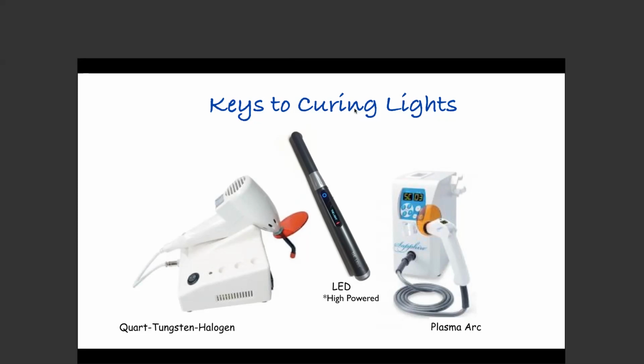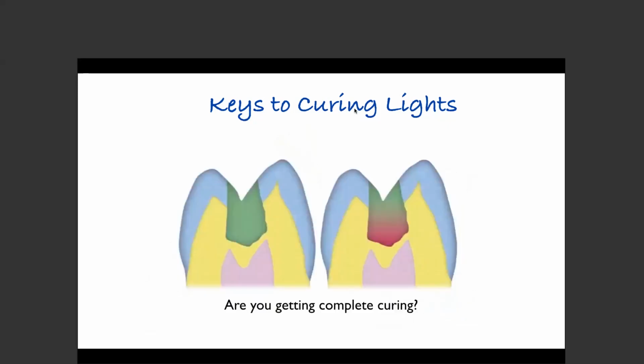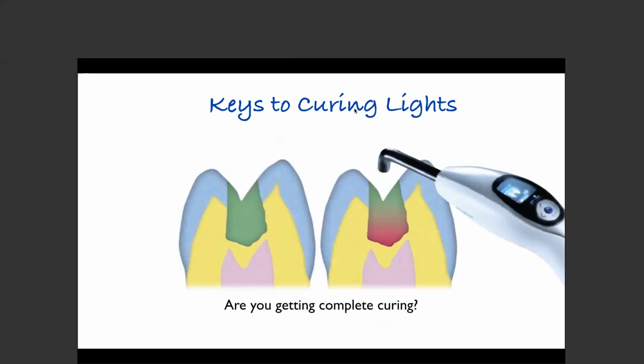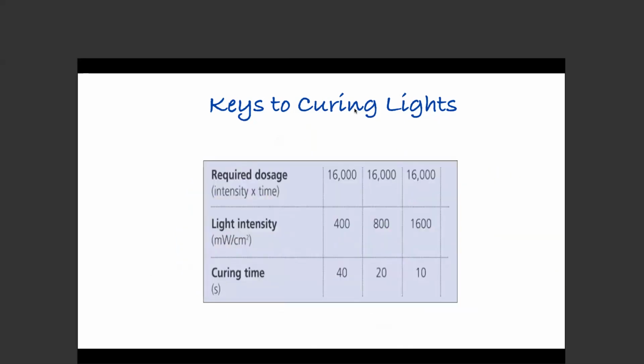And in my world, I believe that those curing intensities degrade much faster over time. The halogen bulb doesn't last as long, doesn't kick out as much power a year from now as it does when a new bulb is placed. So just make sure that you're testing your curing lights, because unfortunately the surface of your composite could be cured, but the reality is that deeper down into your class 2 areas, your composite may not be getting cured, and therefore the patient could have increased risk of sensitivity, recurrent decay, those sorts of things. So make sure that your curing system is appropriate.